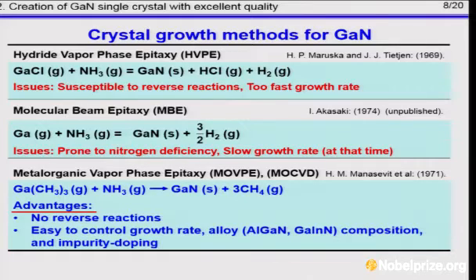In the case of HVPE, crystal quality was degraded by an appreciable reverse reaction, and the growth rate was too fast to fabricate device structures with thin layers of nanometers.